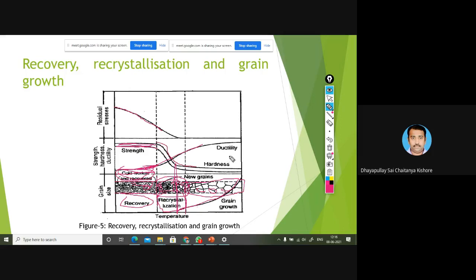If there is an increase in ductility, then its connected hardness and strength are reduced. So due to the increase in grain growth, that is the concept related to recovery, recrystallization, and grain growth. Once you are increasing the temperature, at the recrystallization point, it starts the increase in the grain sizes. If there is an increase in grain size, that will affect the ductility: the coarse grains always have good ductility, but their strength and hardness values are reduced.